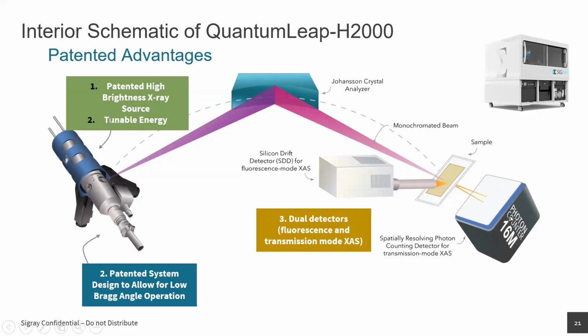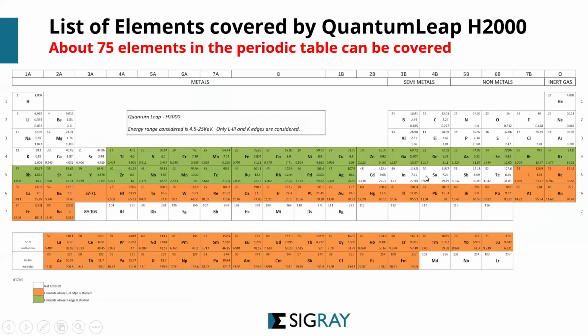And it allows us to run it under transmission mode using a photon counting detector, as well as using the SDD detector to look at the fluorescence mode. We're going to see that it can cover a wide range of materials. In fact, 75 elements can be covered using this particular equipment, from titanium all the way to high Z elements.